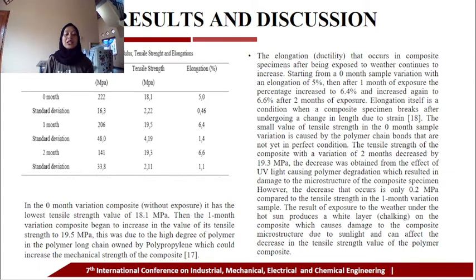In the sample without exposure, it has the lowest tensile strength value of 18.1 MPa. Then the 1-month variation composite began to increase in tensile strength to 19.5 MPa. This was due to the high degree of polymerization in the long polymer chains of polypropylene, which could increase the mechanical strength of the composite.